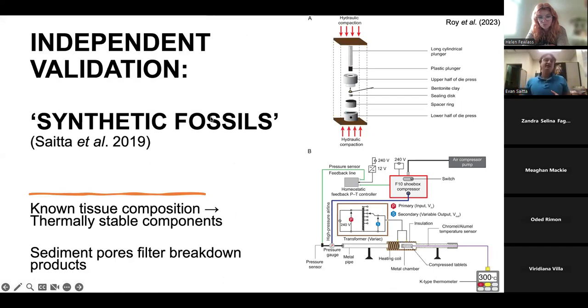But what I'm really interested in is using maturation as a form of independent validation for conclusions you make when studying the fossils. And the work I do here, I informally call synthetic fossilization, where I take a sample, I bury it in the sediment, compact it with a hydraulic press, and then use a heated coil in a maturation chamber that is pressurized with gas. Gas could be air, gas could be inert nitrogen, to then undergo the actual thermal maturation under high heat and high atmospheric pressure. And so what you're doing is you're taking a known tissue with a known composition, and then you're exposing it through simulated diagenesis to hopefully infer what components are thermally stable and which are not.